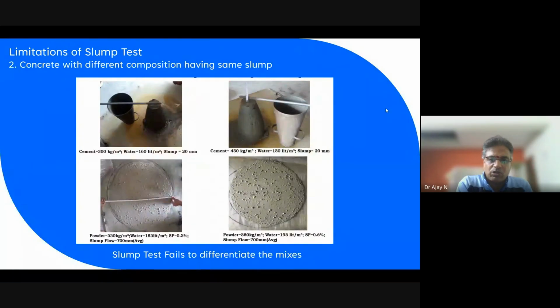And more or less both give almost the same particle distribution, and the aggregate suspension is almost the same. Both will be more cohesive mixes, but the values are almost the same, 700 mm. So the slump flow or slump test does not differentiate the mixes, because when we alter the cement and water, it should give some different values, but it's not giving different values. But fundamentally,